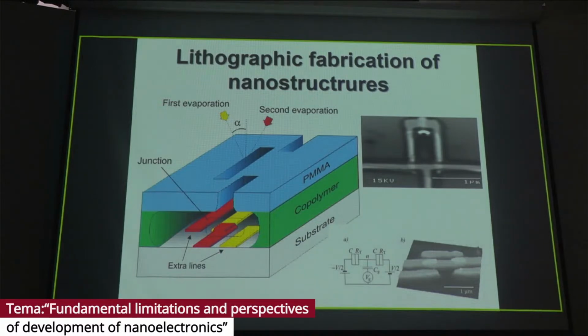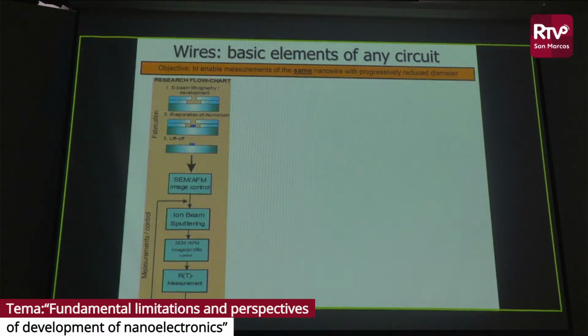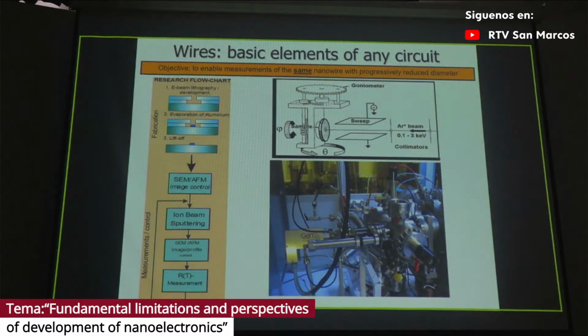So the conventional method is lift-off e-beam lithography. We fabricate our nanostructures, for example, like this, and then we want to reduce the characteristic dimension. For example, let's speak about how to make the cross-section of a nanowire smaller. First, we study the nanostructure with all available analysis, let's say optical microscopy, SEM microscopy. If we do not see any problems, we make a measurement, let's say measuring resistance or IV characteristic at low temperature. Then we take the structure out of our measuring system and put it into an ion beam chamber. We wobble it under a very diluted and low-energy ion beam of inert gas.